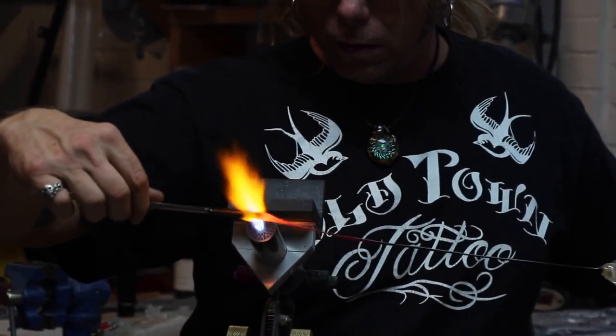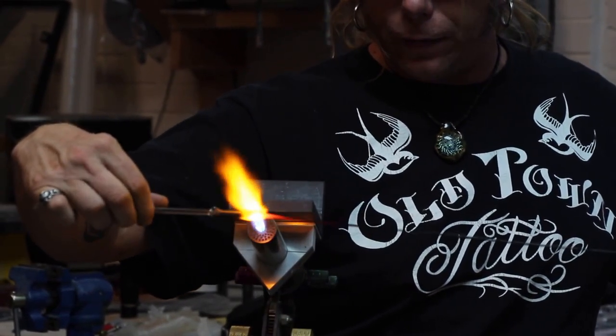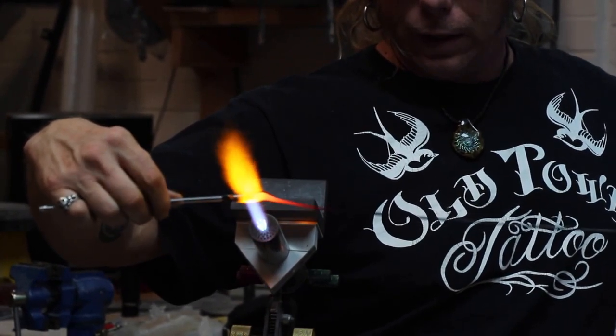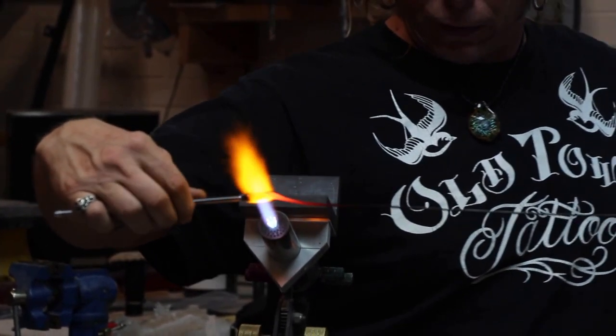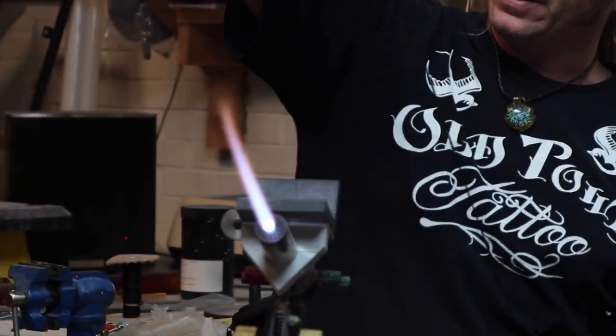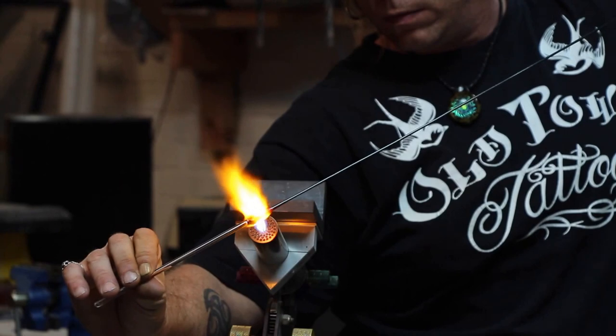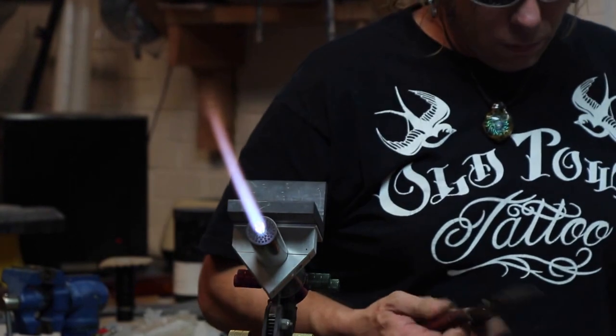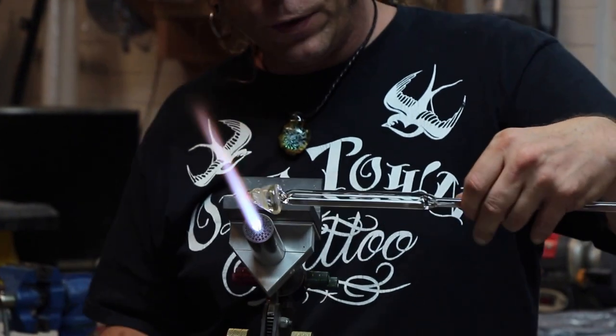3 millimeters is about best, 4 max. 4 is going to be a little much because you get quite a lot of heat to melt that evenly. It's key to keep the heat lower, with less off-gassing, which is the motivation for backing this way. Let that stand cool for a second.